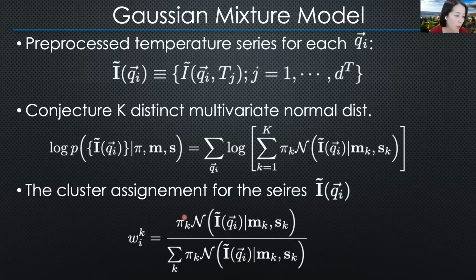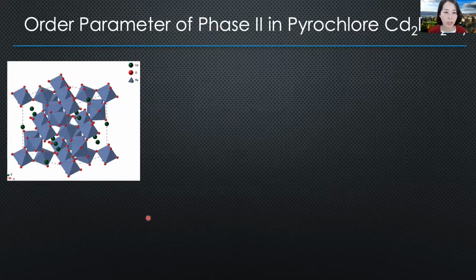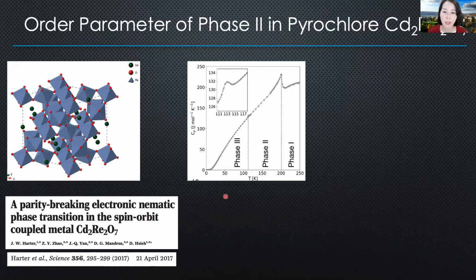Once we developed this approach using the titanium diselenide data, we applied it to pyrochlore cadmium rhenate. It's a pyrochlore superconductor, the first known pyrochlore superconductor, and it has a phase diagram where the symmetry of the high temperature phase is well known. But at about 200 Kelvin, it goes through a very well-defined, sharp, continuous phase transition. And what this lower temperature phase is, what the lowest temperature phase is, and what this blip means is still not very well understood. Now, superconductivity occurs somewhere down here out of this phase, and it is obviously of interest to try to understand these phases.